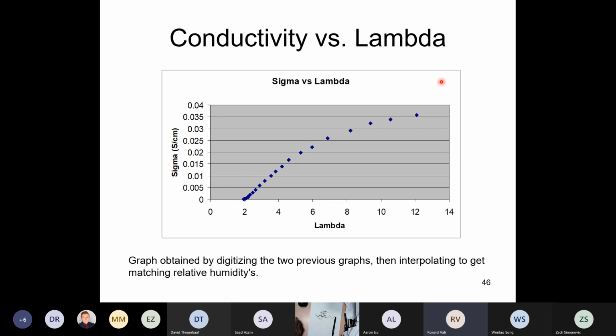Well, it doesn't shrink and contract in a fuel cell because it's in a stack and it's well compressed. Turns out to be very reversible, Ron. It's really incredible. You can flood your cell, and then in a few minutes you can flow low humidity air and low humidity hydrogen to it and dry it out. And you can over dry it and have lousy performance because the conductivity is down here somewhere. And then you can rehumidify the gas flows and move back into this region. We're going to come to this in a minute.